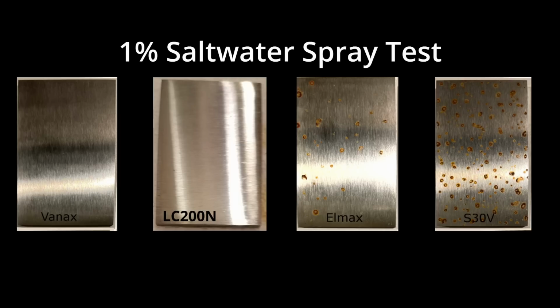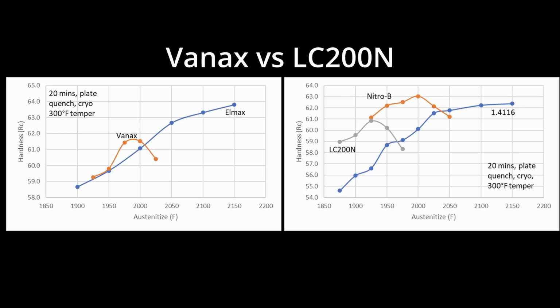So yeah, Vanax, the corrosion resistance is really high, just like LC200N, and that's the advantage it's giving you versus Elmax, even though the Elmax can get to higher levels of hardness. But seemingly, either because the proportion of nitrogen to carbon is a little bit lower in solution with Vanax versus LC200N, so more carbon, less nitrogen, but it also has more carbonitrides in it.